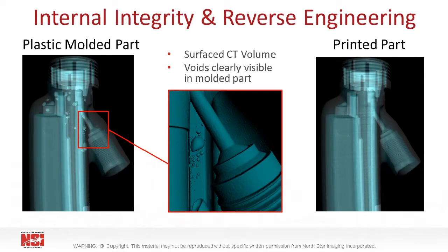This is a great example where CT can be used not only for evaluating the internal integrity of a part, but also for reverse engineering. On the left-hand side, we see a surfaced volume of a CT scan of this plastic injection molded part. It's real obvious that there's a substantial amount of void showing up here. When we put this semi-transparent viewing to this surface, you can rotate the volume around as if it's a transparent part that you can just see inside to inspect.